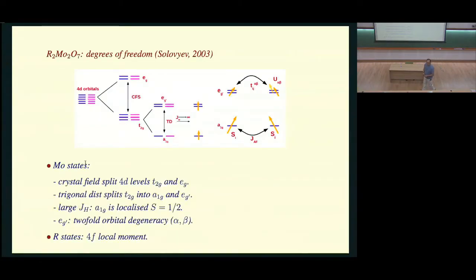Well, your crystal field diagram reminds me a little bit of the rare earth nickelates, which are perovskite materials. In those materials, the electron lattice coupling is extremely important. For example, you get a bifurcation of the octahedra into two groups with different polaronic contractions of the octahedra. I don't know anything about your molybdates, but I was asking, do you think any such coupling might play a role in these systems?